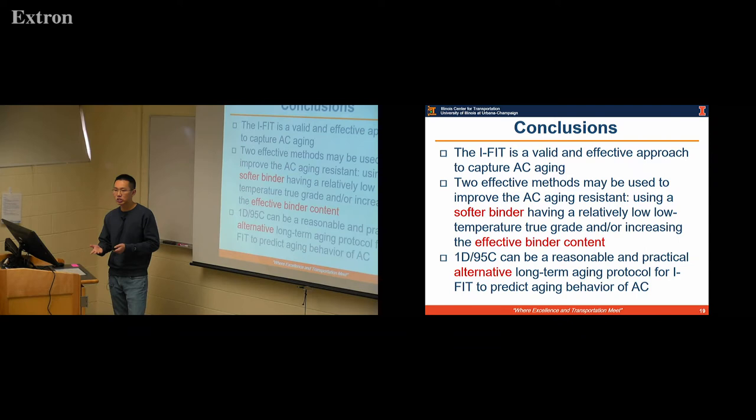But 1D95C, compared to this aging protocol, cannot save you that much aging. But here, I want to say that in some scenarios, especially for contractors producing their already designed mixes, they may want to fine-tune their mixes. And they do not need to wait that long to have a conclusion. So 1D95C can be used for them to predict their performance after the real long-term aging protocol, which is 3D95C, we introduced before in the presentation.